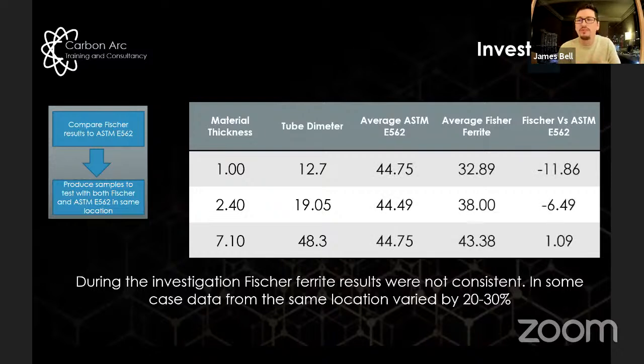So what we then started to do was, right, well, processes are fine, our training's fine, our material's fine. Is there a fundamental issue with Fischer ferroscope testing which is giving us an incorrect value? So what we did is we took a load of different results here. And as you can see, on average, the Fischer ferroscope reading on the small bore materials was quite a long way out from the actual ASTM point count results. And it was worse the thinner the material got and the smaller diameter it got. Now, this is three sort of cross-sectional results I've shown for you here on 1 millimeter, 2.4 millimeter, and 7.1 millimeter thick tube.